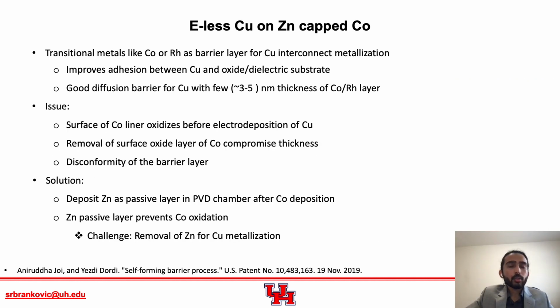Now, the first project I'm going to talk about is electroless copper deposition on zinc-capped cobalt substrate. There are several transition metals like cobalt or rhodium which are being explored these days as a barrier layer for copper interconnect metallization. These new materials like cobalt or rhodium as a barrier layer could improve adhesion between copper and oxide or dielectric substrate, and they provide a very good diffusion barrier for copper with as little as 3 to 5 nanometer thickness of the metal itself.